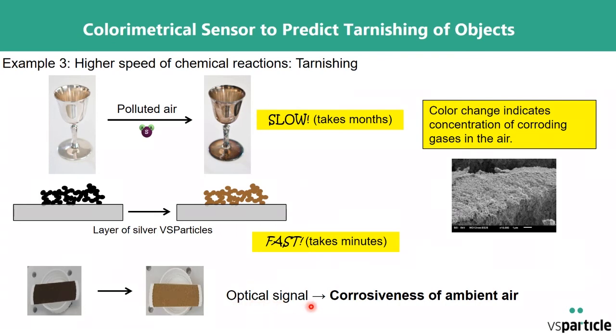use an optical signal, developed out of this color change. Basically, any mobile phone can do that and get the red, green, and blue components of the color, and then give you a measure of the corrosiveness of ambient air, for example, with respect to silver. And that tells you if a silver object is going to tarnish or not. Tarnishing takes a couple of hours or even months, and our small particles are much, much more reactive, so we can predict whether it will tarnish or not within minutes.